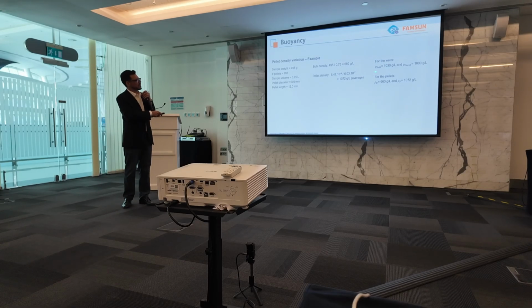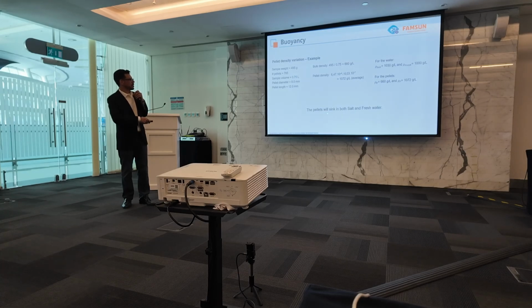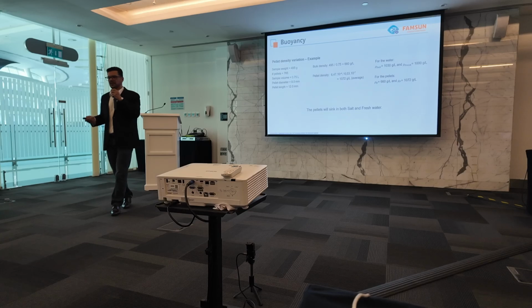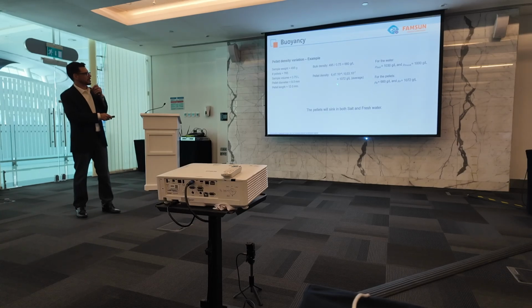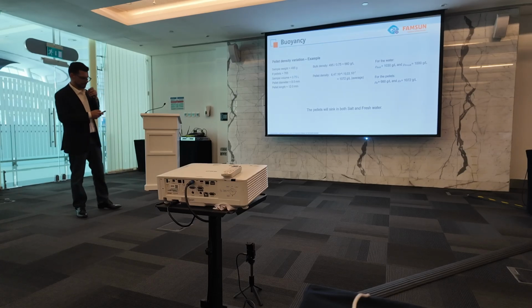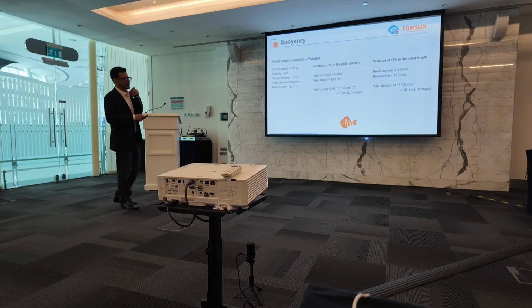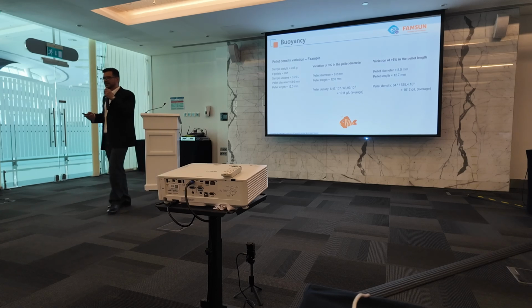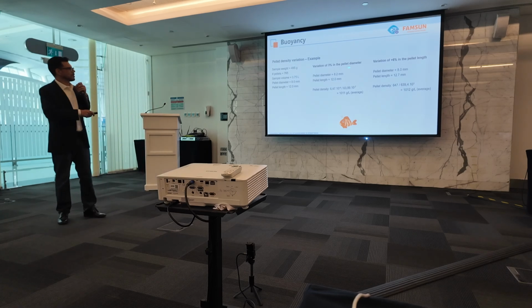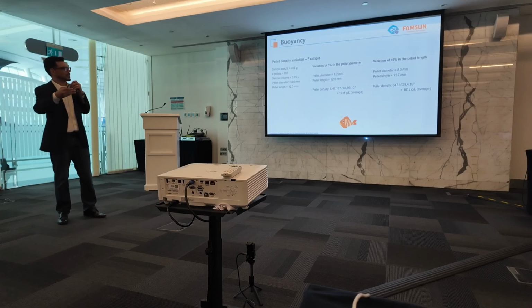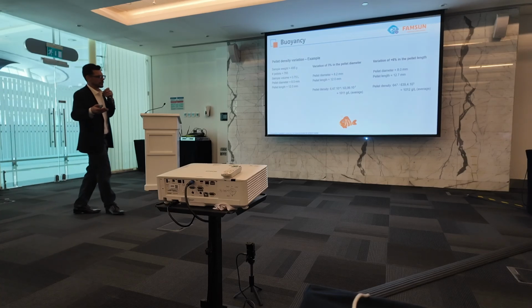So if we look at the water, the salted water has a density of 1030. Fresh water has a density of 1000. So in this case, this pellet would sink in both salt and fresh water, because its pellet density is bigger than these two, either salted or fresh. But now we have some variation because the process is not perfect. This variation may occur still in the extrusion process or during the drying. Not all the product will shrink in the same way.